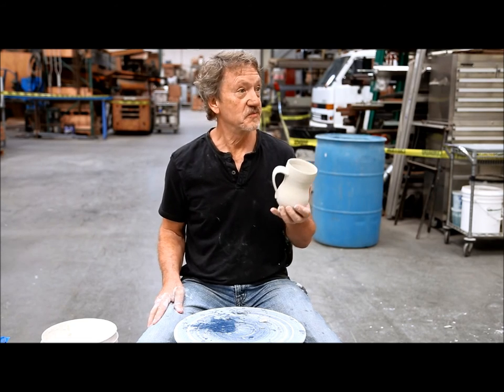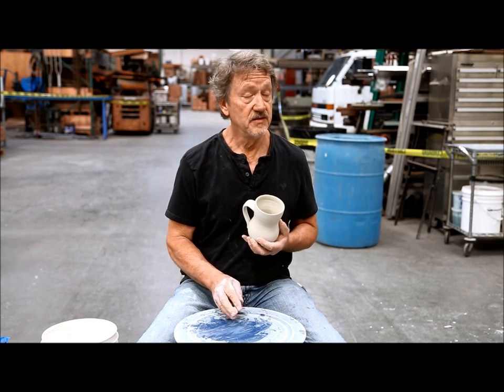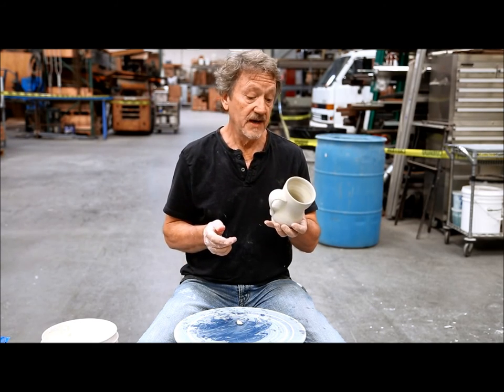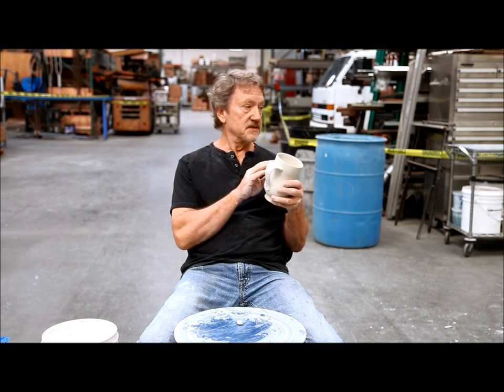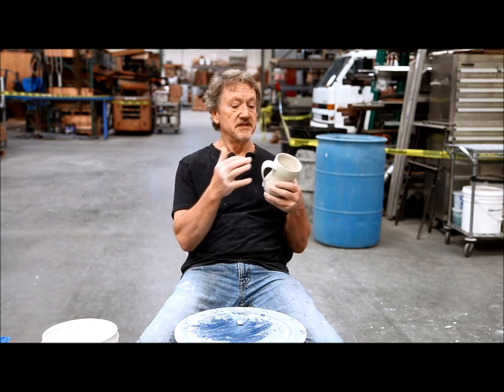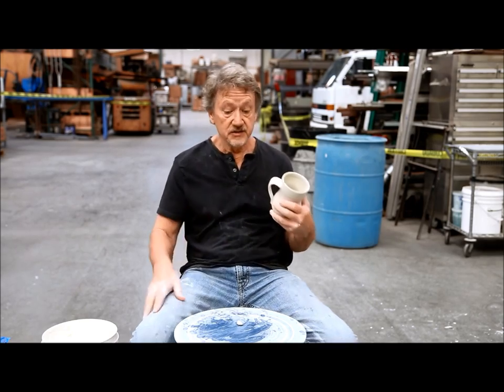You don't have to cover this with plastic for four weeks — you set it right out. The odd thing about Vegas is that things dry faster there because it's so hot and dry, and they never crack. You can't set them out in the sun, but there's just no humidity. When I get through pulling these handles, Pat Horsey and I used to put them straight in the kiln for a bisque fire at this stage. It's better — if you're going to blow something up in the bisque, it always blows up because it's not all the way dry. There's a skin on the outside and the steam can't escape, so it blows. A convection oven is the idea — if you're going to bisque fire wet, put a fan to circulate the heat. It's a very slow dry — the way they dry commercial bricks.